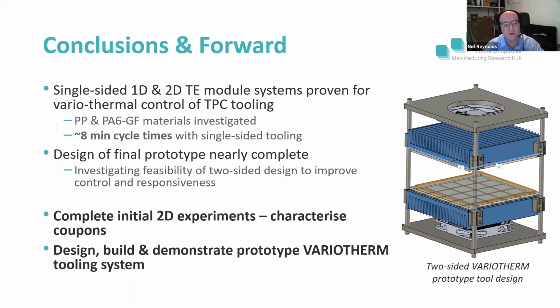But the ultimate conclusions are that we've developed these 1D and small 2D systems that have shown certainly sub-8 minute cycle times for a 2 millimeter thick structural laminate, which is very encouraging. It shows that the technology might have an interest, and of course there's this potential control of crystallinity that we could do, effectively measuring the onset and peak crystallization during the process. So there could be some real-time control aspects introduced into this system that we think is of interest.